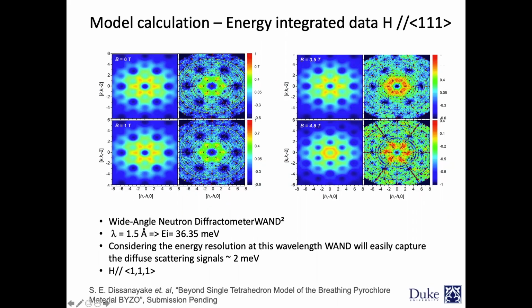Which means that when we are at high energy or high fields, it looks like we can capture the physics with the single tetrahedron model. But when we go to low energies and low temperatures, that's when the single tetrahedron model fails, and practically what we have is that the tetrahedrons start talking to each other. So we have intertetrahedron interactions, which can introduce these quasi-particles that can host the Weyl magnons.